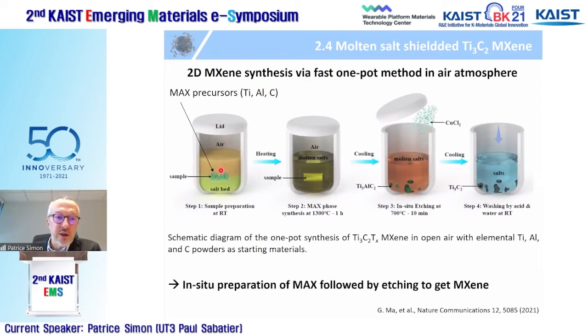What you do is that you start from MAX precursors. You mix titanium powder, aluminium powder, carbon powder in the stoichiometric ratio. You put this pellet that you prepare by pressing into a crucible, and you put here your salt bed. When you heat the molten salt, your sample is going to be immersed in the molten salt, and you can even keep air atmosphere. No need to control the atmosphere via nitrogen or argon. And then you prepare your MAX phase during the first step at 1300 Celsius degree.